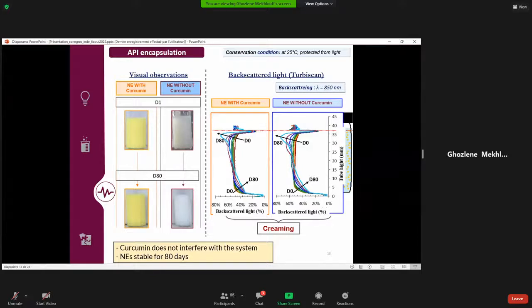However, this creaming is a reversible phenomenon, as the mean diameter in nanoemulsions with and without curcumin did not significantly evolve over time. So we can say that the introduction of curcumin into the oily phase of nanoemulsion does not interfere with the system, and that formulated nanoemulsions are stable for 80 days.